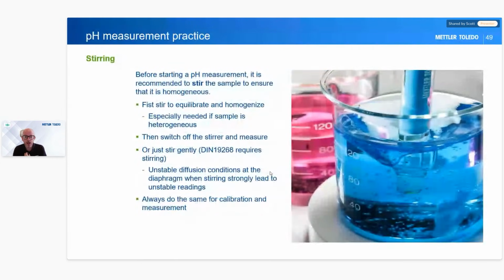The next one is just how to take a measurement. So when we're taking a measurement, we've calibrated, everything's ready to go. So we start taking our first measurement. The first thing we need to do is make sure our sample is homogeneous. So that means everything's well mixed. So we might need to stir our sample first. Not with the electrode. We don't stir samples with the electrode like this. What we do instead is we use a stirrer.